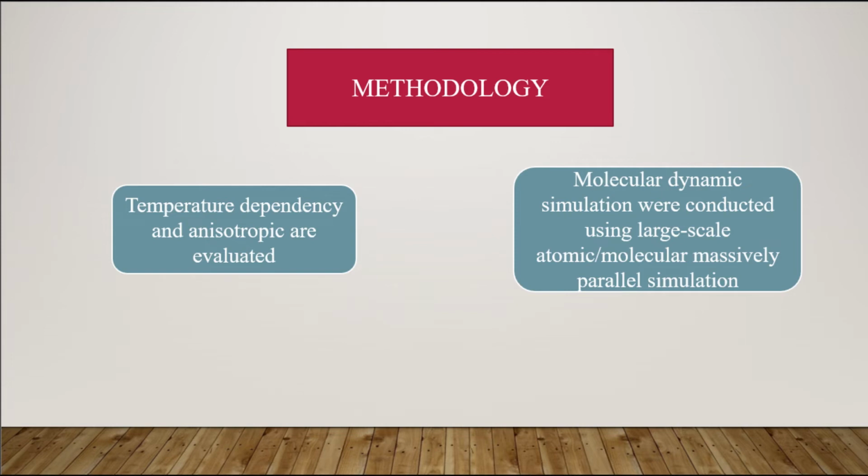There are many methods used in this research in order to evaluate the data from the available numerical and experimental data. The temperature dependency and the anisotropic nature of the material for coefficient of thermal expansion were evaluated with perfect and other impurities configuration. The molecular dynamic simulation was conducted using the Large-scale Atomic/Molecular Massively Parallel Simulator, or LAMMPS.